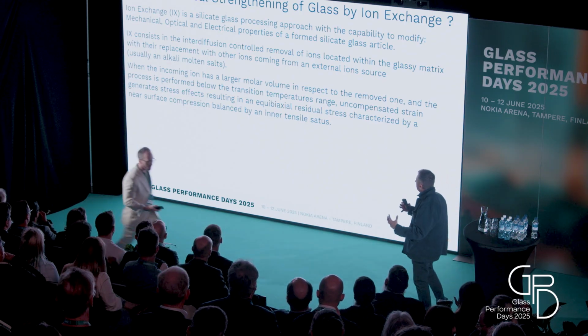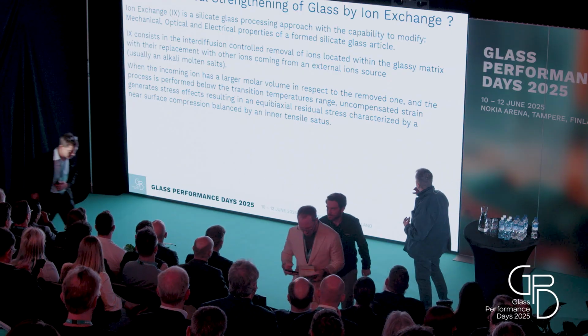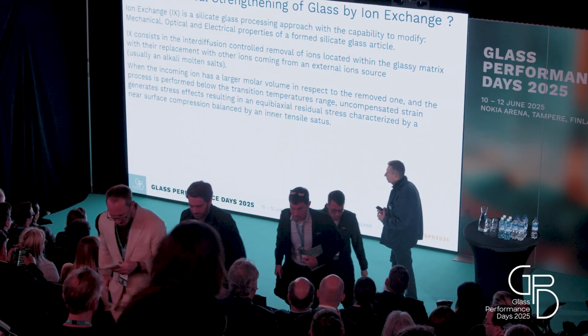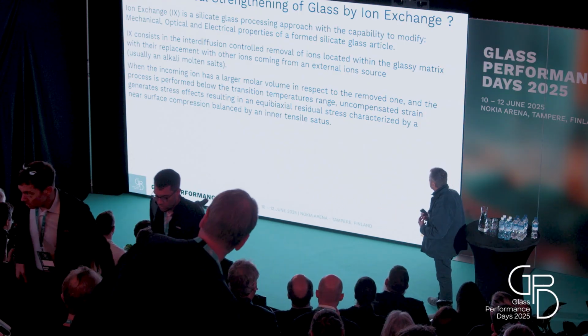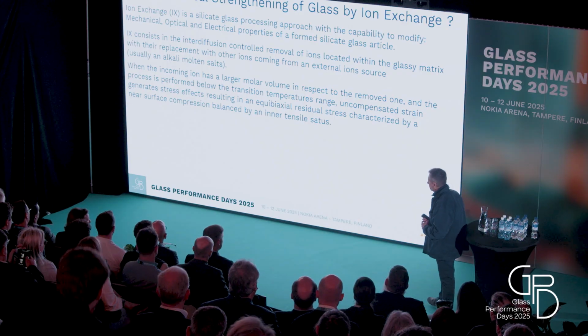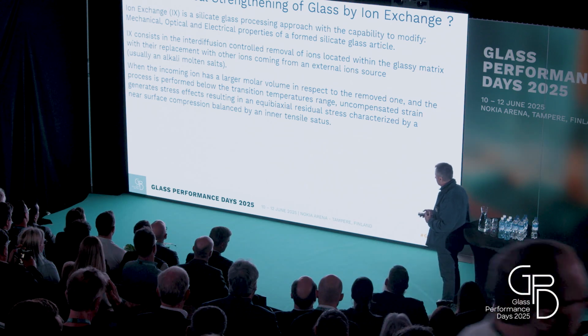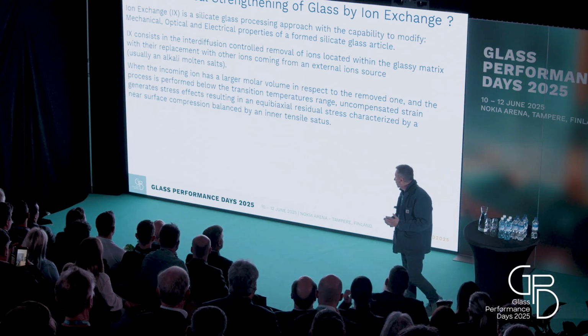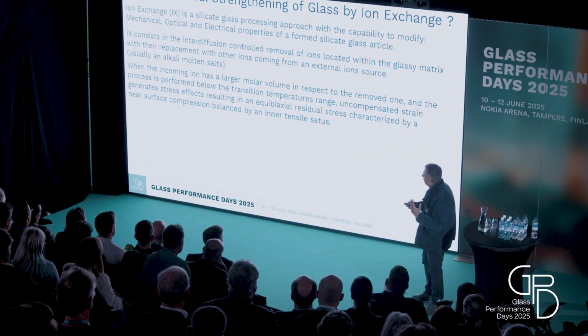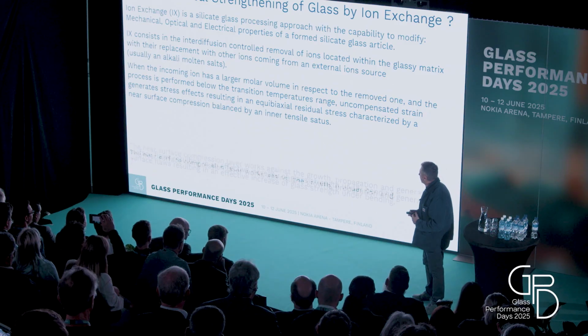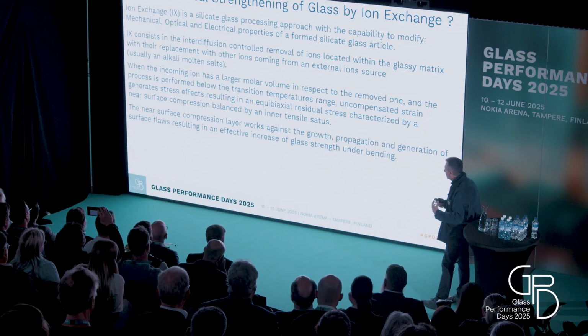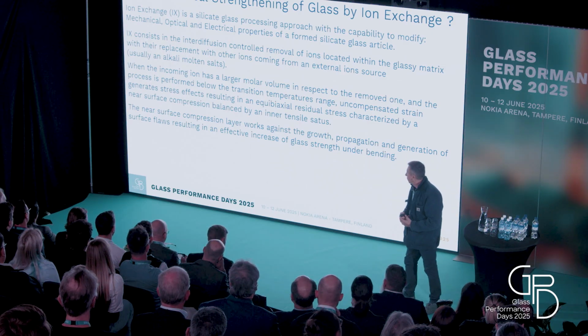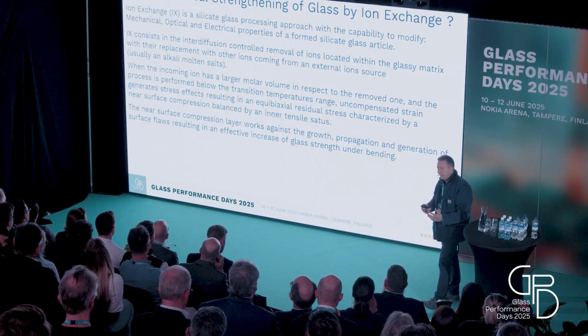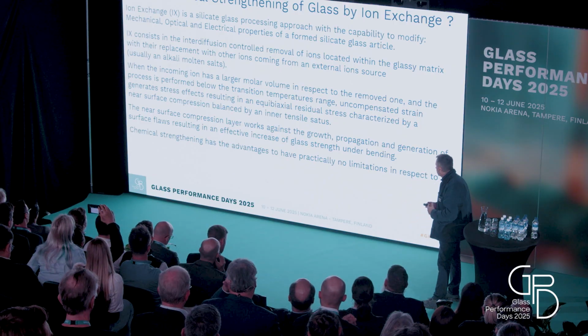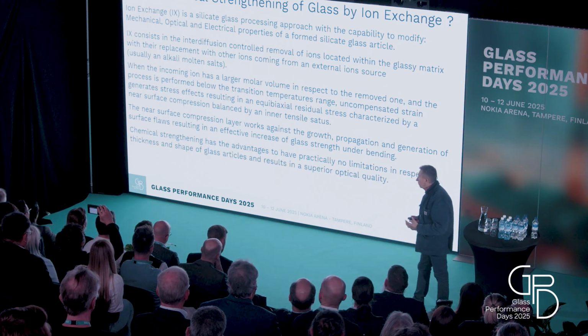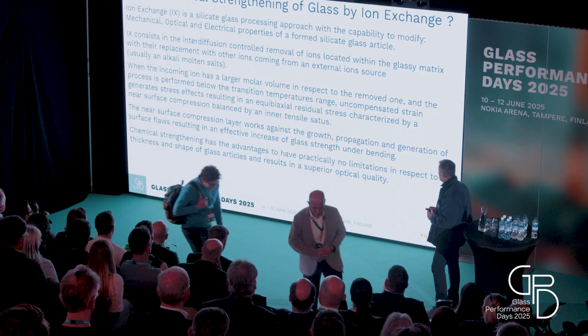When the incoming ions have a larger volume with respect to the removed ones, and the process is performed below the transition temperature range, you will have uncompensated strains, which generate stress. And this results in an equibiaxial residual stress, which is characterized by a near surface compression balanced by an inner tensile state. This is the application of this type of process for mechanical applications. The near surface compression layer works against the growth, the propagation, and the generation of surface flaws, and this results in an effective increase of glass strength under bending. Chemical strengthening has the advantage of having practically no limitation with respect to the thickness and shape of glass articles, and results in a superior optical quality.